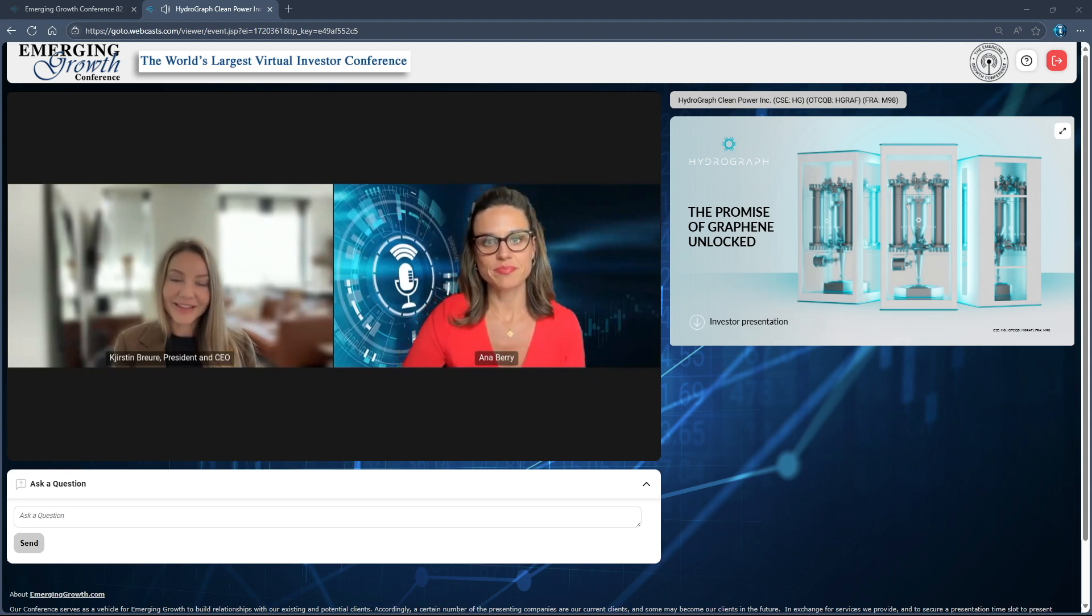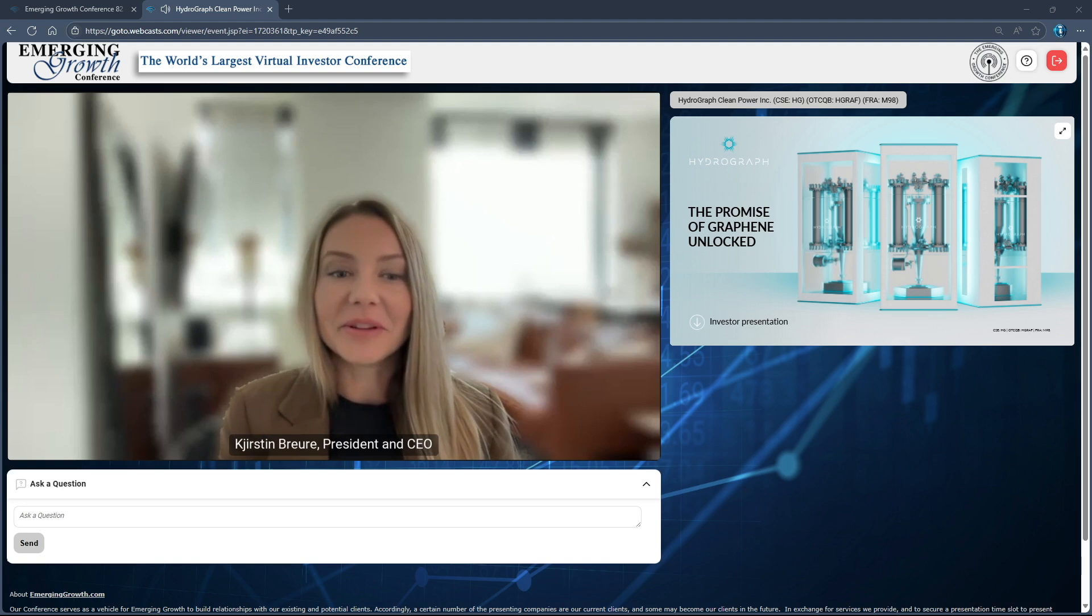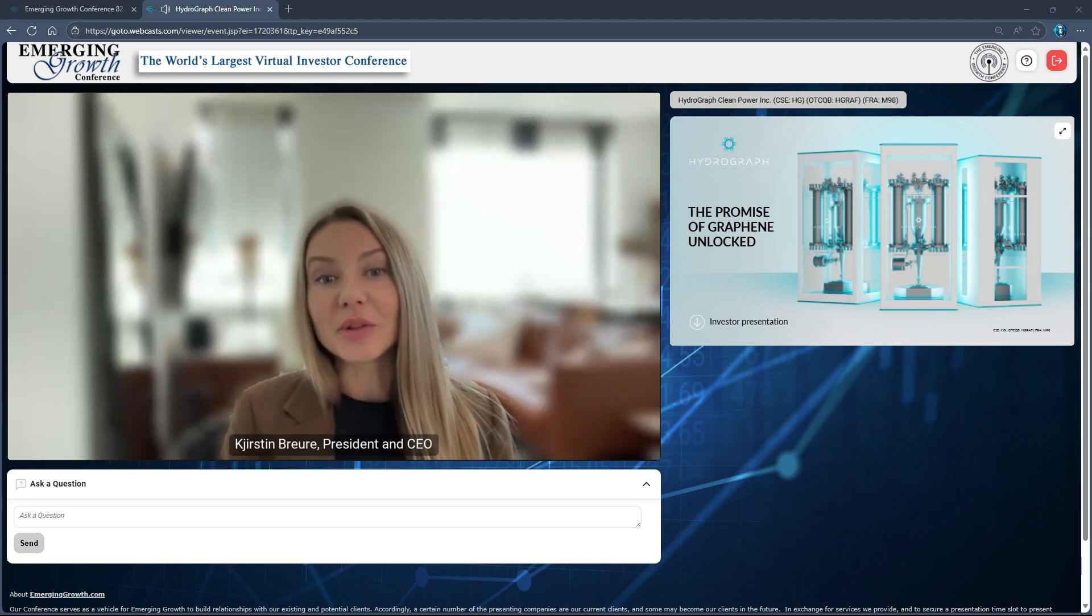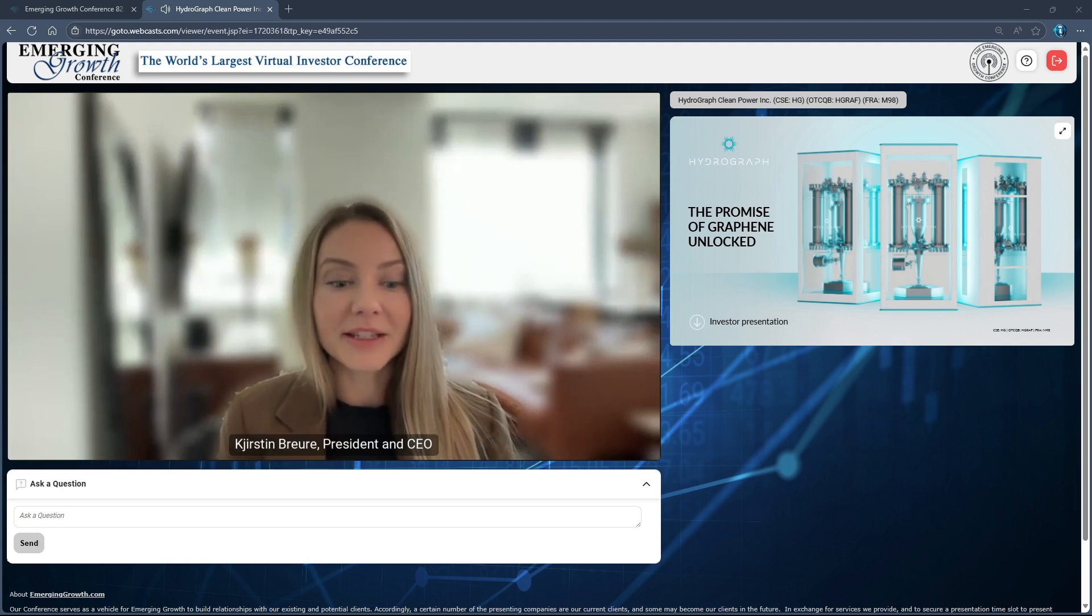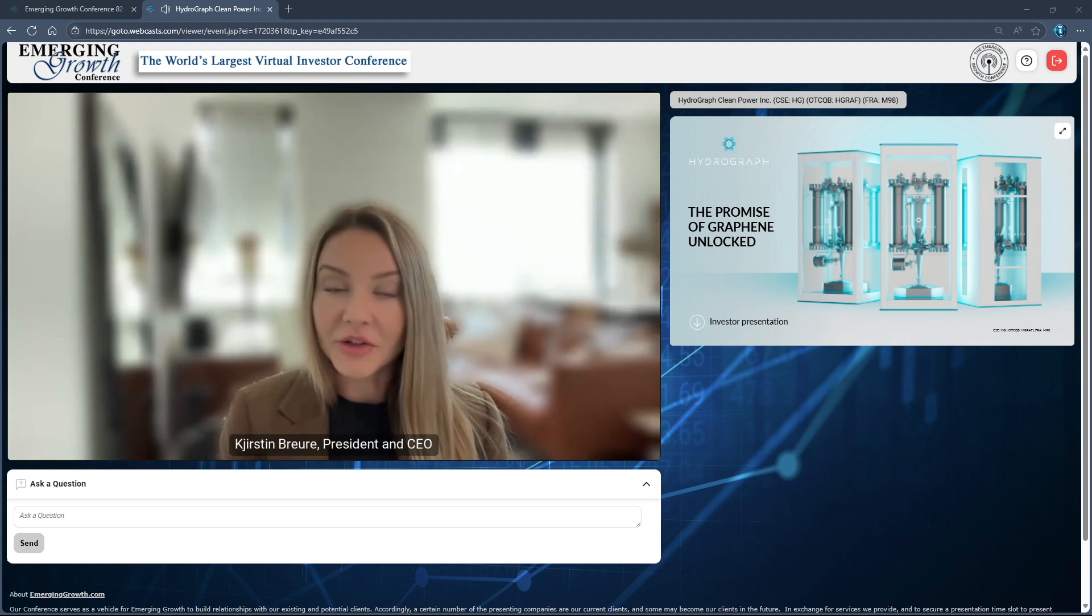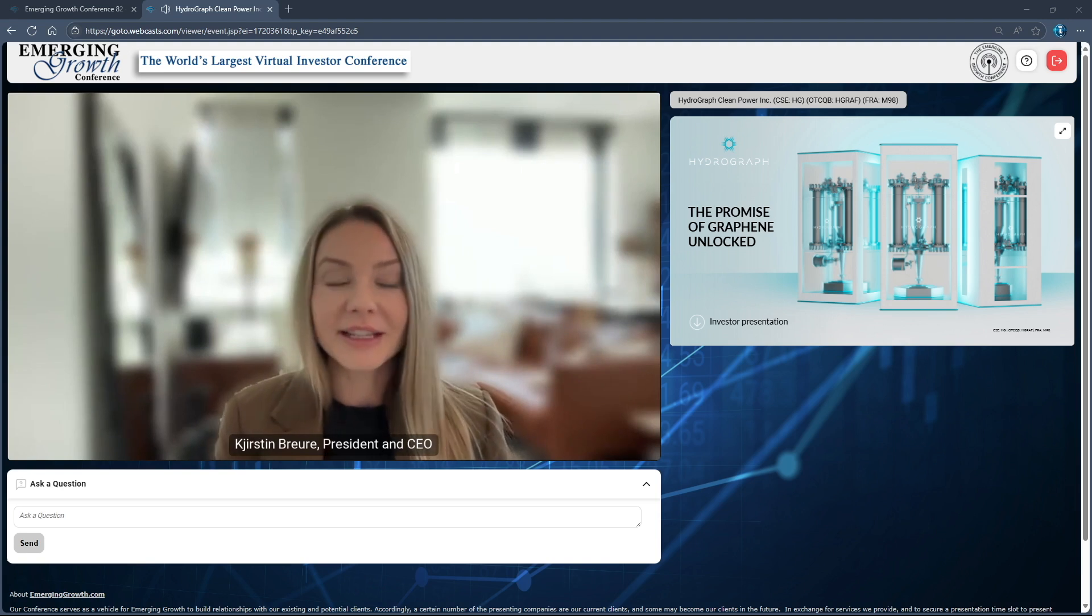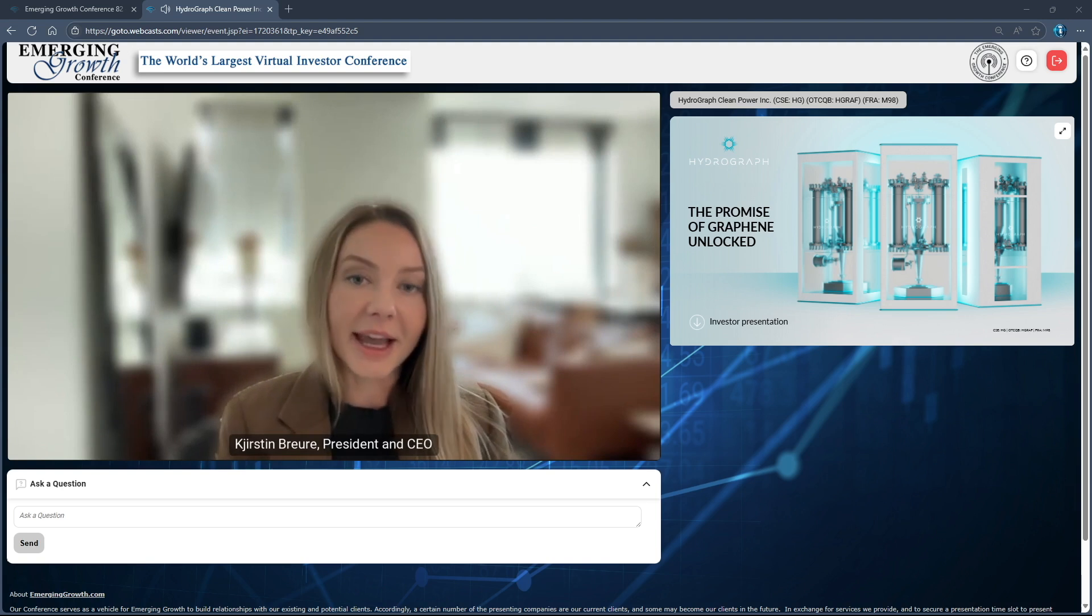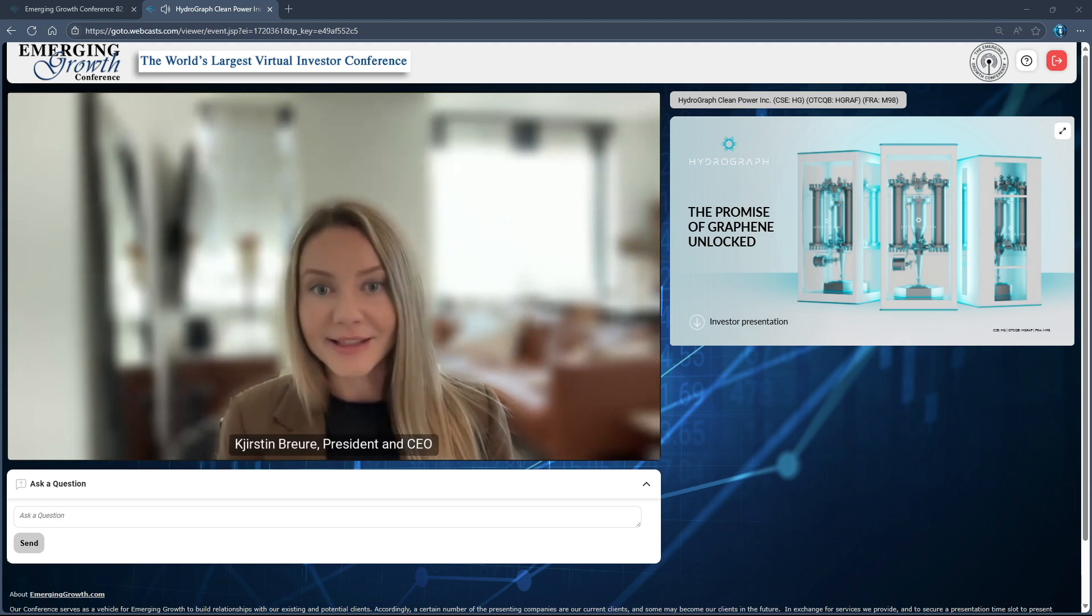Welcoming President and CEO Kjirstin Breure. We have a patented explosion synthesis process which is quite as it sounds - we effectively pump into steel chambers acetylene and oxygen, ignite that gaseous mixture with sparks from an electrode, it destabilizes the molecules, and then we're able to convert the carbon that was in the gas into pristine graphene.